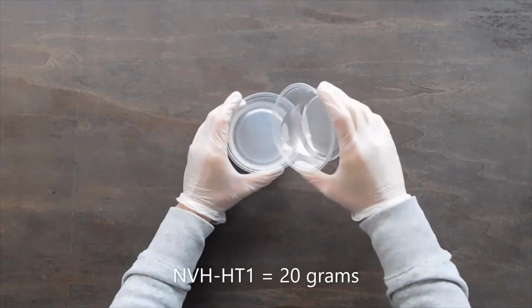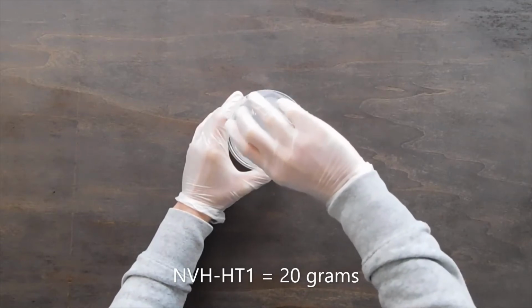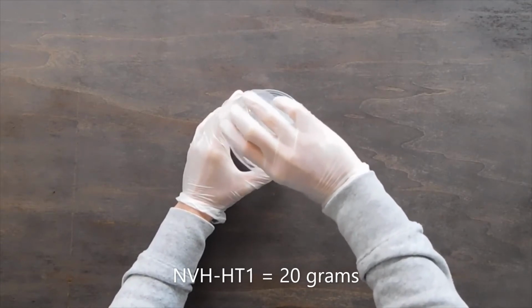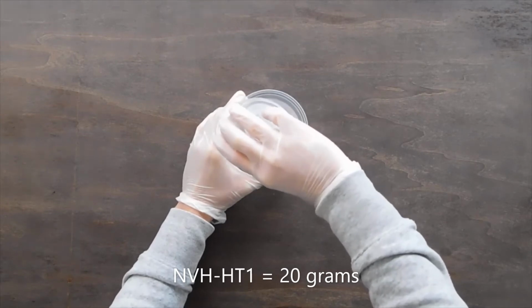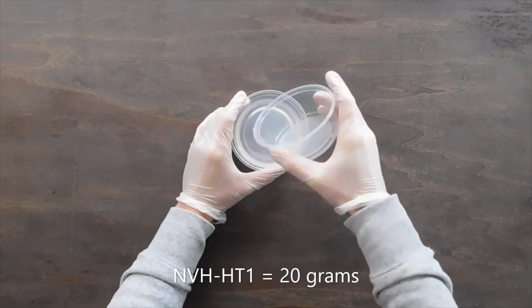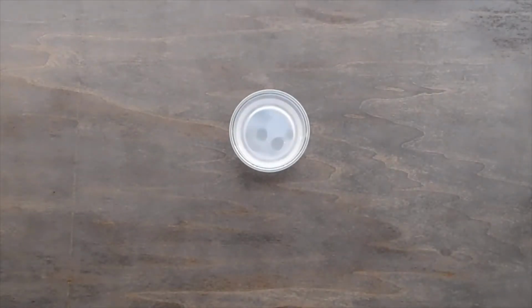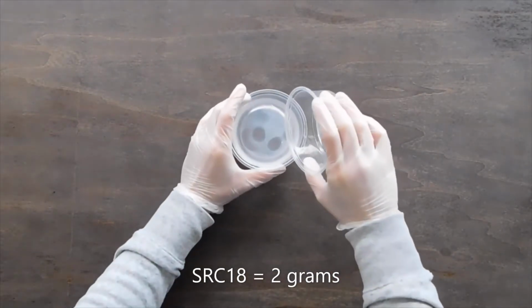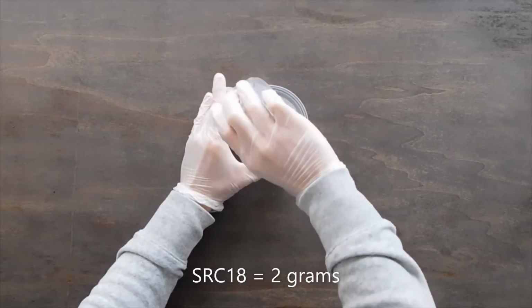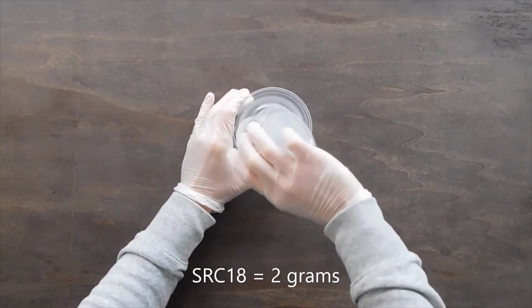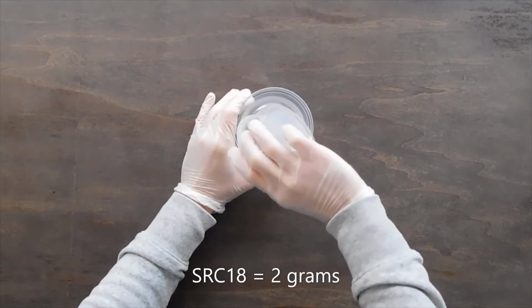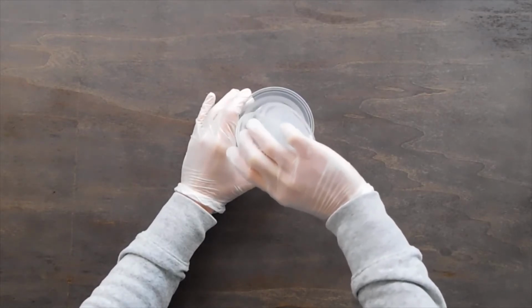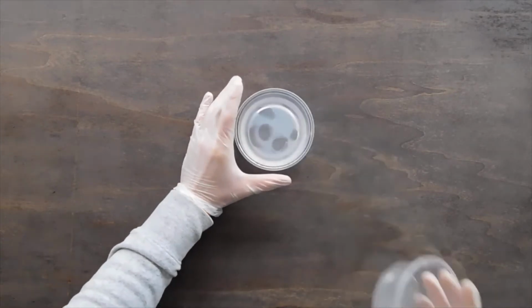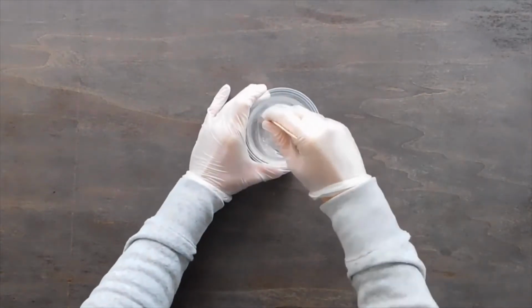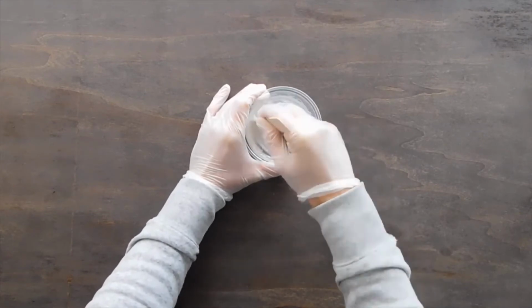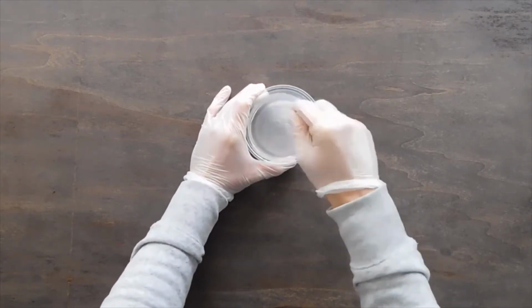Steps 5 and 6. Adding modifier and catalyst to the NVH PSA1. For the sake of time in this video, I went ahead and pre-weighed the modifier and SRC18 catalyst. Since I used 80 grams of NVH PSA1, I will add about 20 grams of NVH HT1 modifier and 2 grams of SRC18 catalyst. This ratio of components corresponds to the purple data series in the marketing bulletin. Next, stir the liquid thoroughly until the modifier and SRC18 catalyst are well mixed with the NVH PSA1 adhesive.